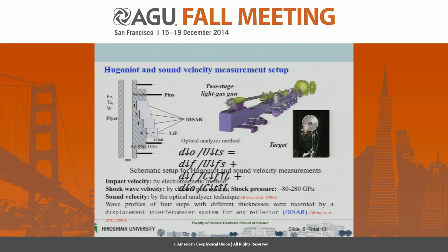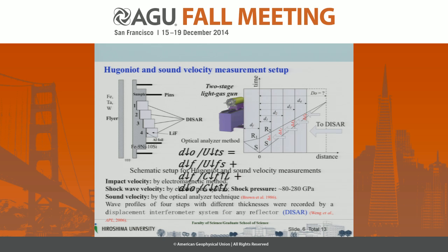In order to measure the sound velocity of our sample, we used the optical analyzer method. This method is based on a relationship between the velocity and the distance at which a reflected rarefaction wave overtakes the shock wave in the target. So if we measure the overtake distance, we can use this relationship to get the rarefaction wave velocity. This rarefaction wave velocity is the sound velocity we wanted. We used a target with 4 steps of 4 different thicknesses, and the wave profiles of the 4 steps were recorded simultaneously to fit the overtake distance.